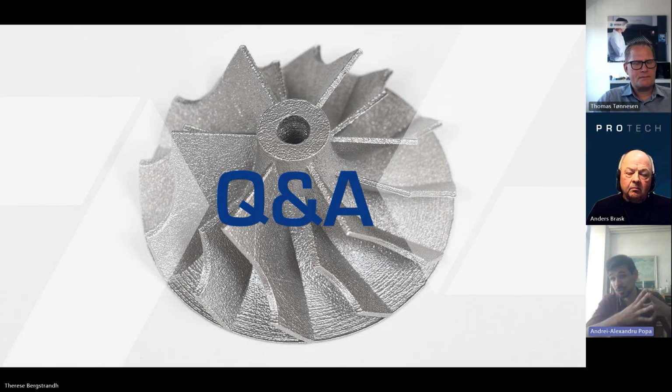What's also interesting, except for the predictive thing, is the monitoring. So we are also applying now for funding, and we are probably very close to getting it, in terms of investigating how the melt pool behaves during print. There's in situ monitoring that can be done in a variety of ways. You can basically use the reflecting and the refracting part from the laser to monitor how the heat is building once you're melting these powders.